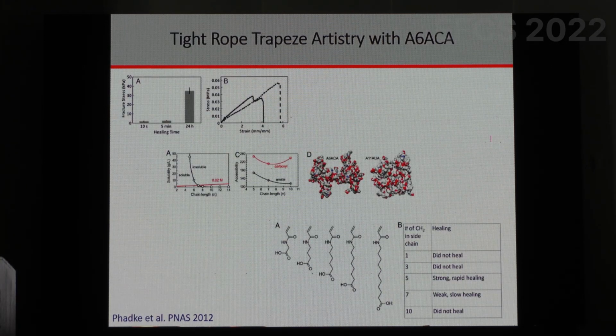So these are some very nice simulations that we did, but what is most exciting is that the length of the spacer group decides whether they will stitch across the interface or not. If you have too small a spacer group, they actually do not heal. The interface does not heal. If you have too long a spacer group, again they do not heal, right? In fact, what we see is that they fold back into themselves rather than stretching across the interface. And it's only when you have a certain amount of CH2 groups in the spacer group that they actually start binding to each other. So see how beautiful this, again, delicate balance is.